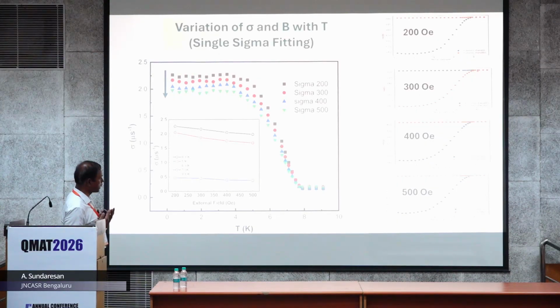To understand and get an idea about the symmetry of the order parameters, we plotted the sigma independently at different fields, and you can see as you increase the field from 200 to 500, it decreases. That's what one would expect. What is shown here is sigma versus external field, and it goes with what we expect from this field dependency.